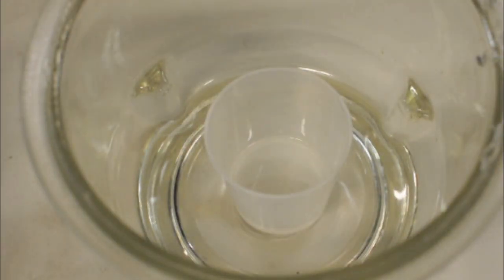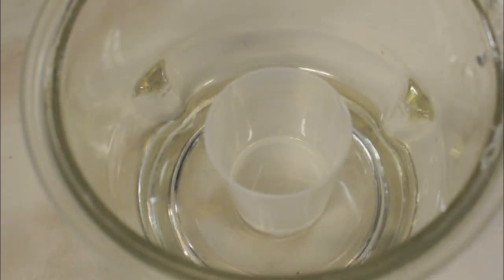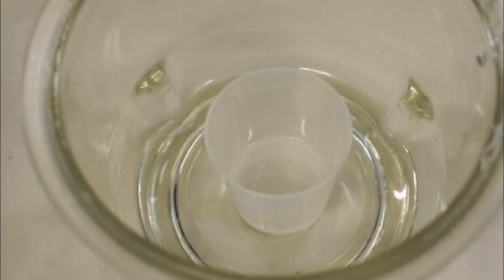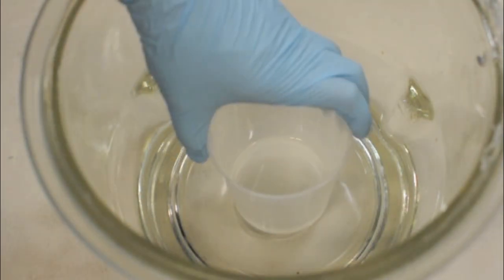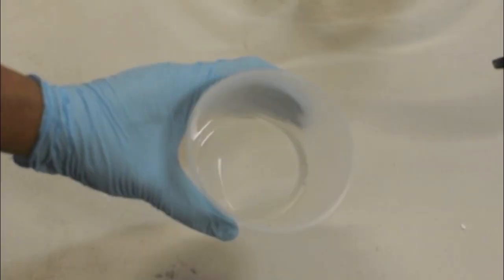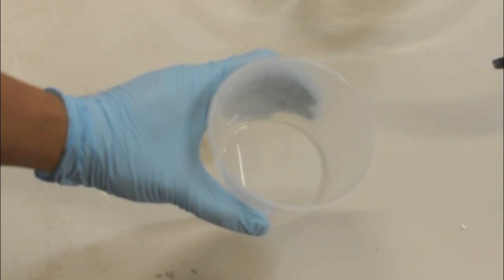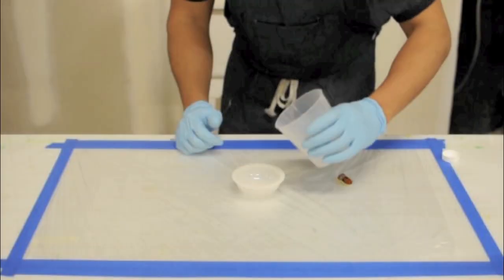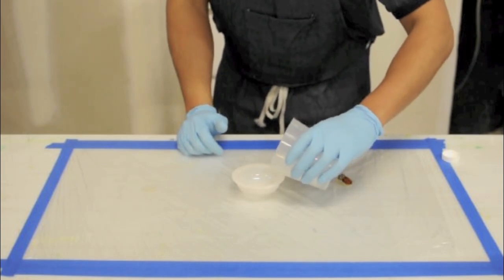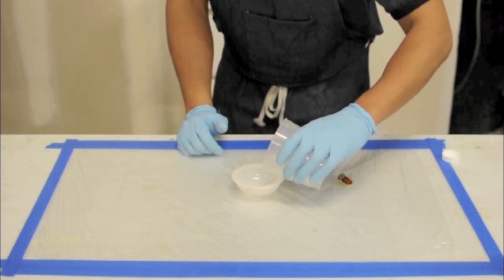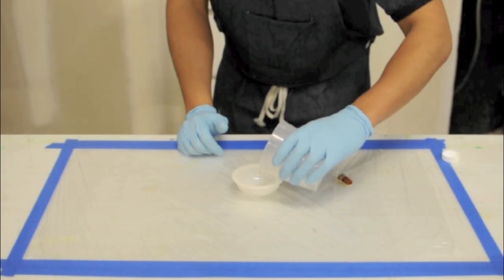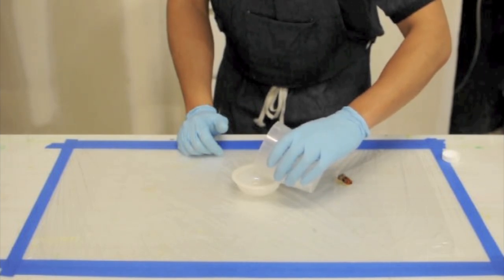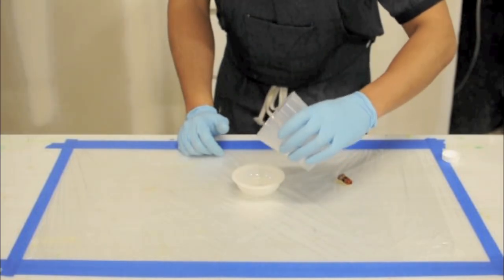Once all the bubbles have risen to the top and popped, remove the vacuum from your degassing chamber and remove the resin. The result should be bubble-free epoxy ready for your casting. When pouring resin into the mold, be sure to pour it slowly so you do not reintroduce air into your casting. And when finished, cover the mold to prevent any dust or dirt from contaminating your casting.